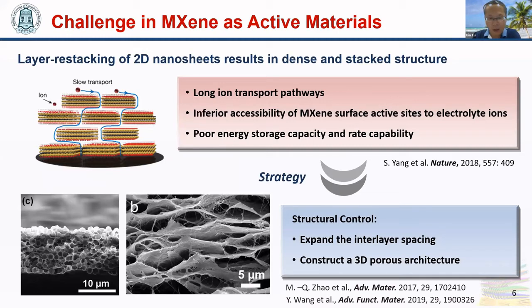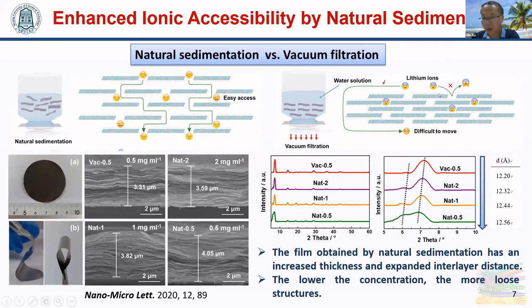To solve these problems, structural control is very necessary. There are two ways. One is to expand the interlayer spacing. Another is to construct a 3D porous architecture. So firstly, to enlarge the interlayer distance, we proposed a very simple but effective method to prepare MXene film by natural sedimentation instead of the conventionally used vacuum filtration. The film prepared by natural sedimentation is freestanding with very good flexibility. SEM and XRD indicate that the MXene film prepared by natural sedimentation has an increased thickness and expanded interlayer distance.